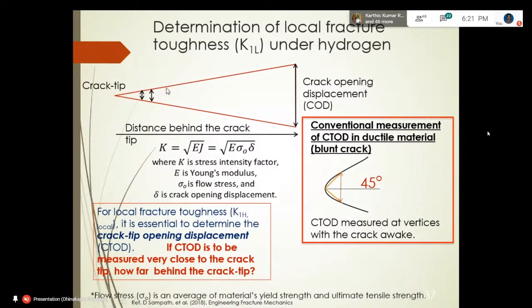to complement the result. Again, we use the topography to measure the local fracture toughness, which, as I told, is the measure of driving force required for unstable cracking. So we used the crack tip opening, but from some distance behind the crack tip, in one case 0.05 and 0.1 millimeters. Some more research is required to find out at what distance we need to measure, but mostly it is to have this 45 degree to meet this criteria.